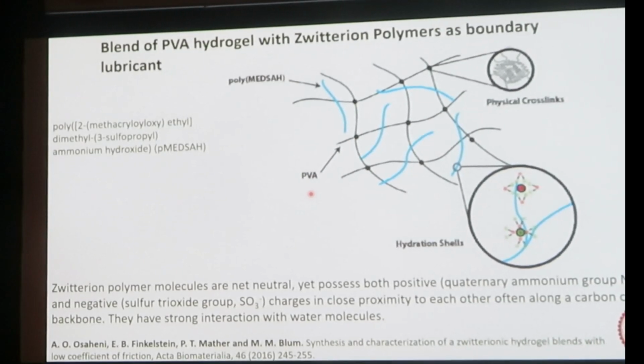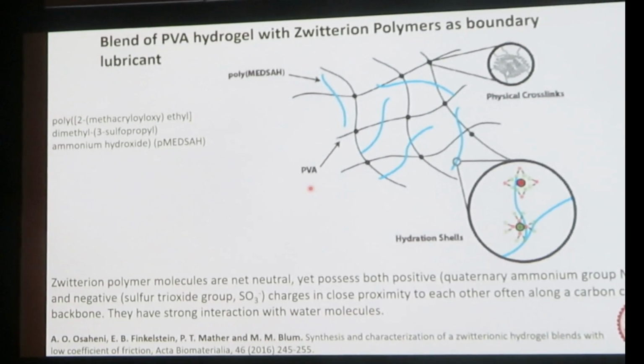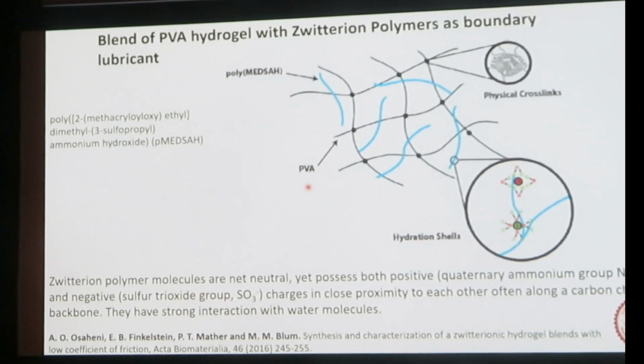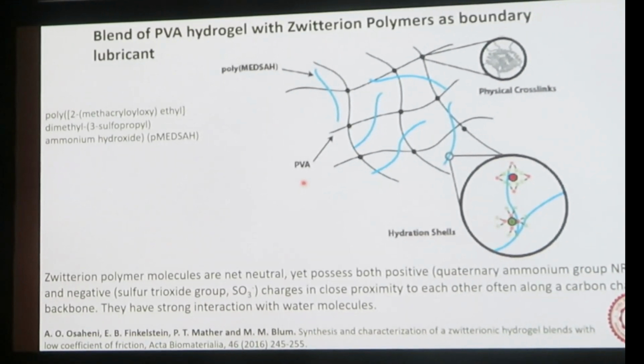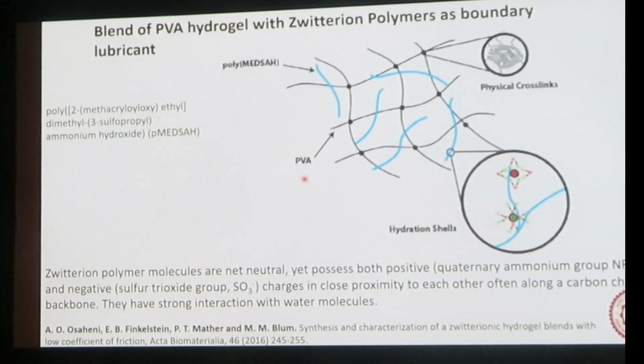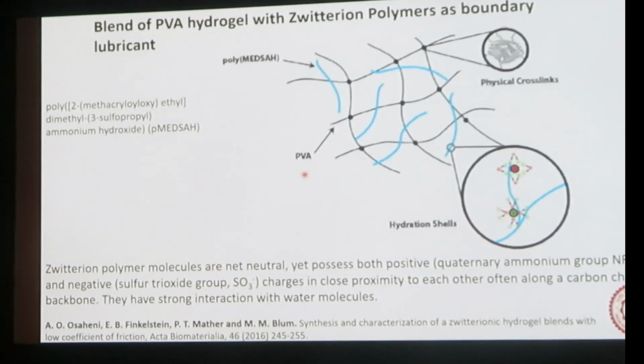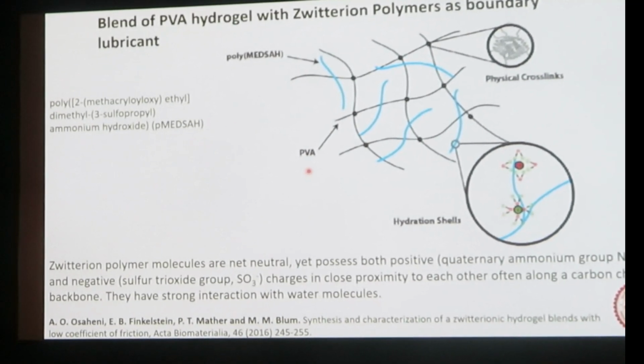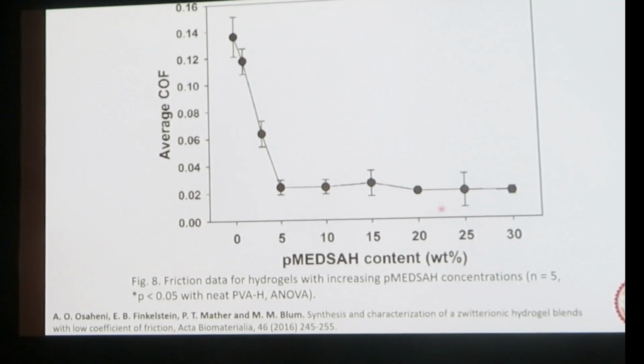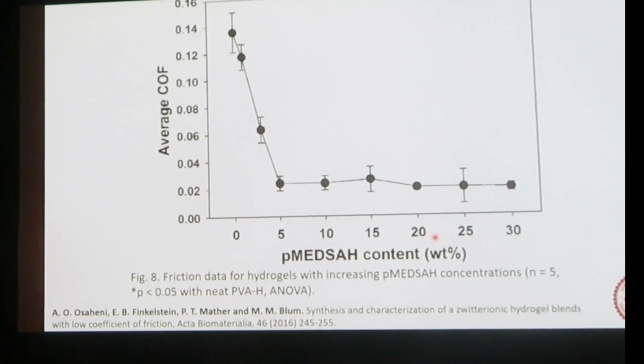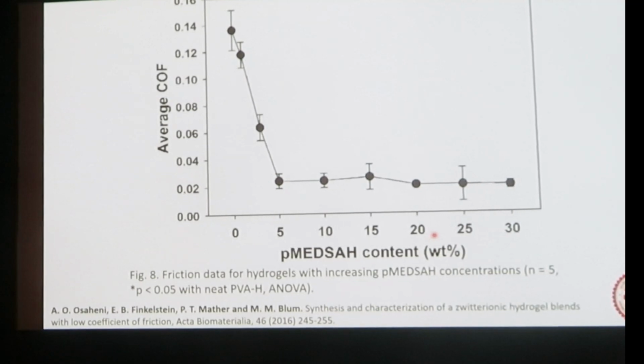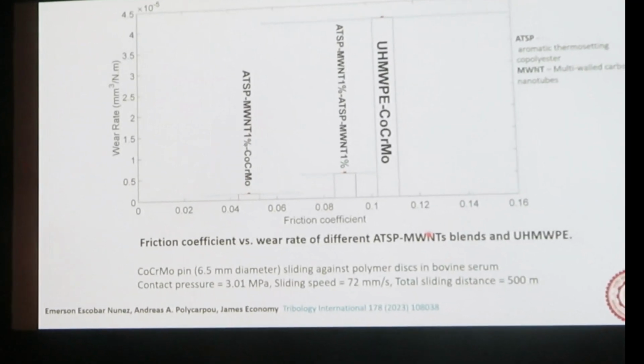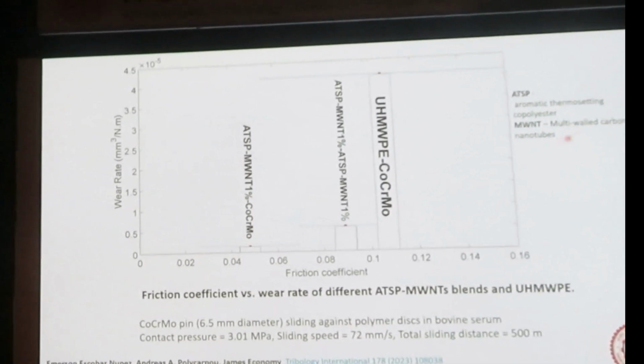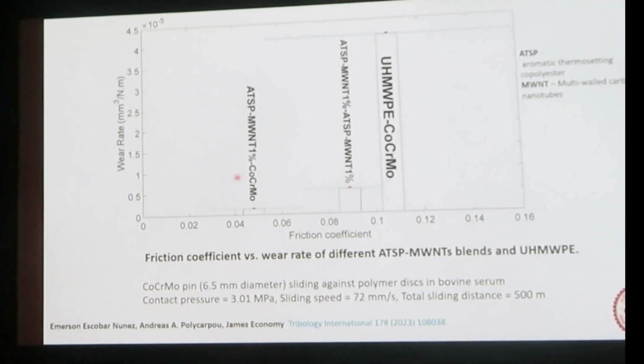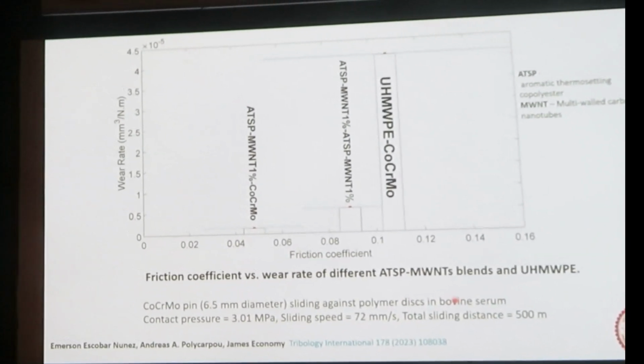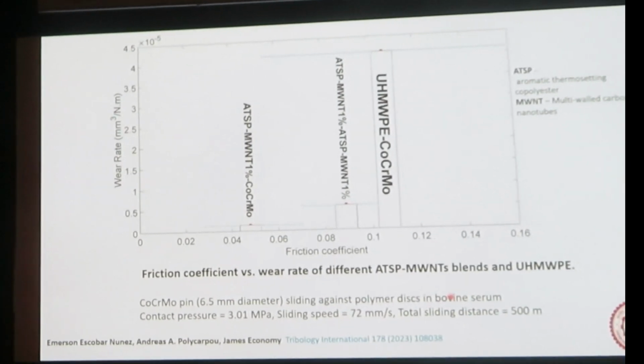Another type of solution people have proposed is adding zwitterionic polymers as boundary lubricants. Zwitterionic polymers are basically polymers which are net neutral, but they do have positive and negative sides because of the sulfonate groups. So just like our natural joints, they will provide lubrication because they attract water molecules. Mixing zwitterionic polymers into hydrogel, they observed that the coefficient of friction is reduced, and to some extent wear also improved, but I don't think the results are enough to give us a clear path. In another paper, an aromatic thermoset copolyester has been used with multi-wall CNT. However, in this research, the conditions are not clinically relevant, unlike what we conduct in tribology, but still there may be some solution here.